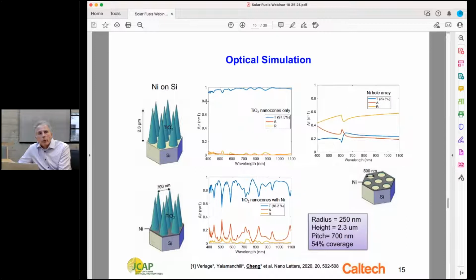You can do that, for example, by producing nanostructures of titanium dioxide that enable resonant waveguiding. You can view this as essentially a broadband waveguide. We can see here the reflectance of this structure. It acts like a beautiful AR coating, and it has a very high transmittance if I, for example, use an opaque nickel film. If I use just a nickel film without the nanocones, you can see the reflectance is quite high.